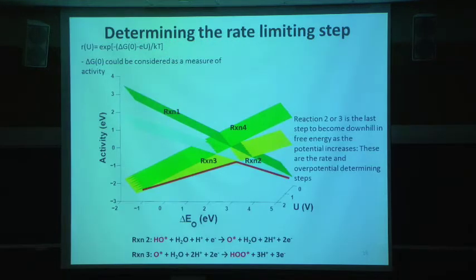So we can go through then, as if you think about this x-axis as a descriptor for the material, you could have something that has a very weak binding energy of oxygen up here, a very strong binding energy of oxygen over here. There's a weak potential dependence over here. We can look at the relative activity of each one of these steps. Whichever one is the lowest is what's rate determining for that particular reaction. And you can see across the whole range of materials here, it's either reaction 3 that's rate limiting or reaction 2 that's rate limiting. So as you start from a material over here that binds very strongly, and you go this way, you go up in activity and then back down.